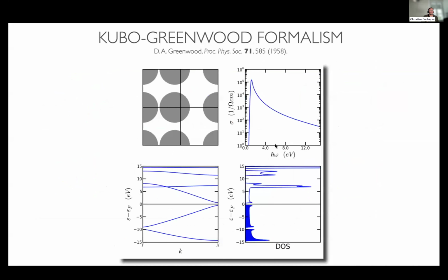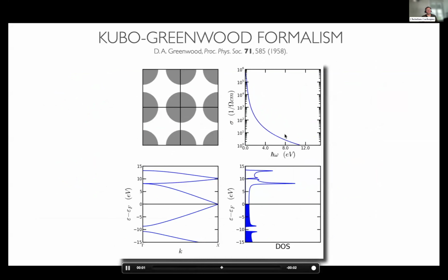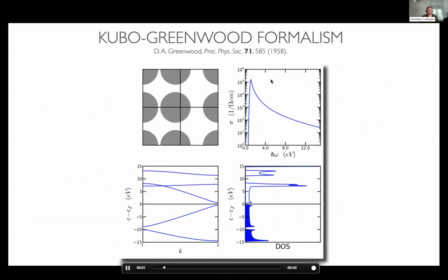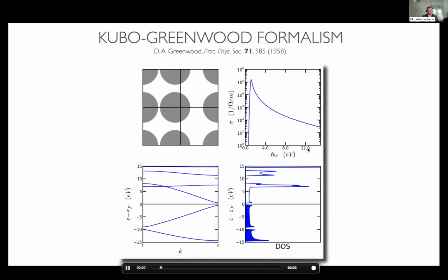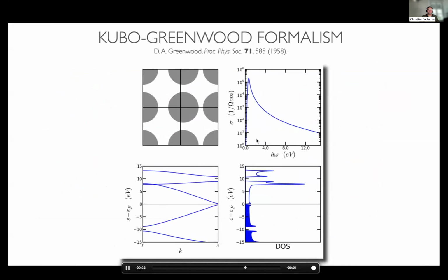And again, for this toy system, you can look at how this would look, just moving one plane of this aluminum back and forth, and you see how the electronic structure changes, opens up, how new transitions are introduced. Then by averaging over these conductivities and going to the zero frequency limit, you can obtain the conductivity.